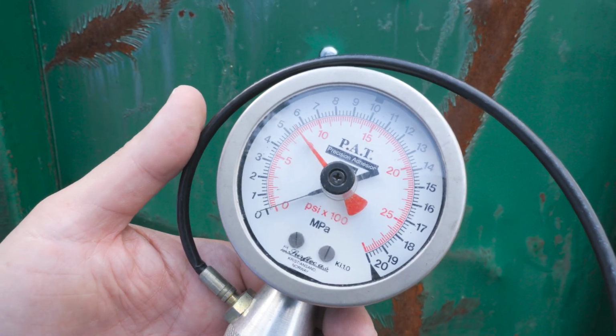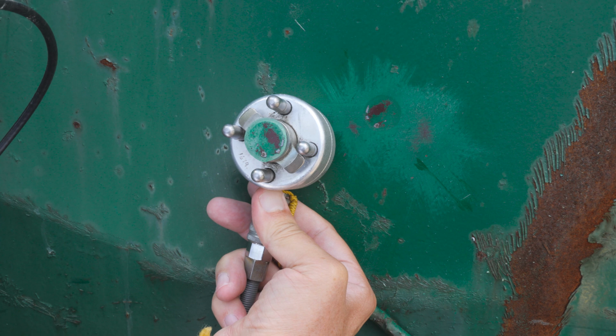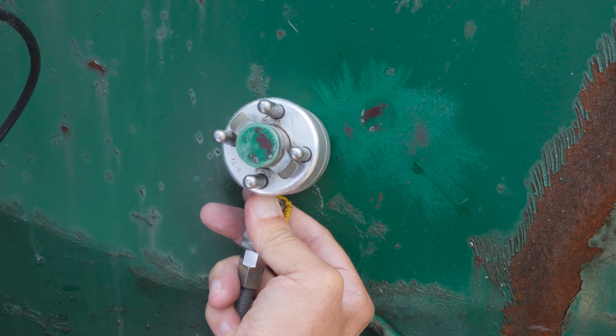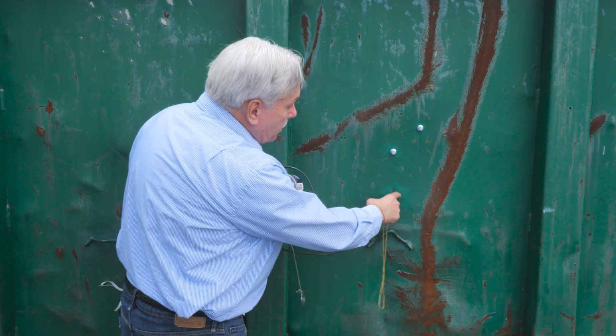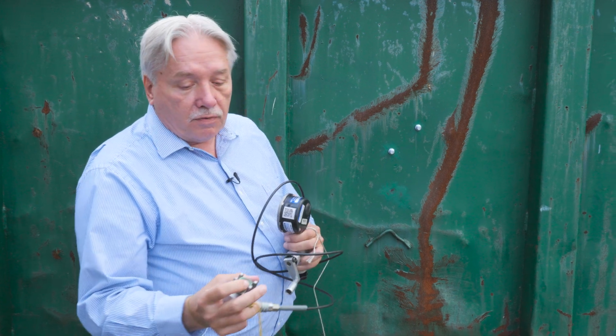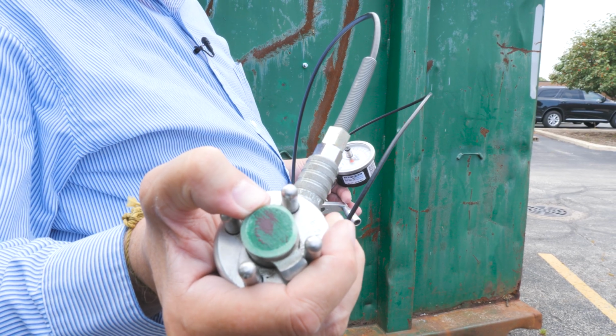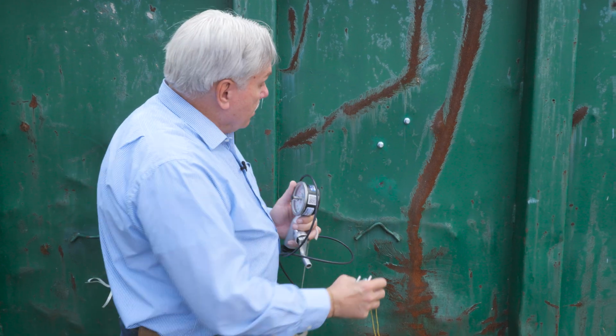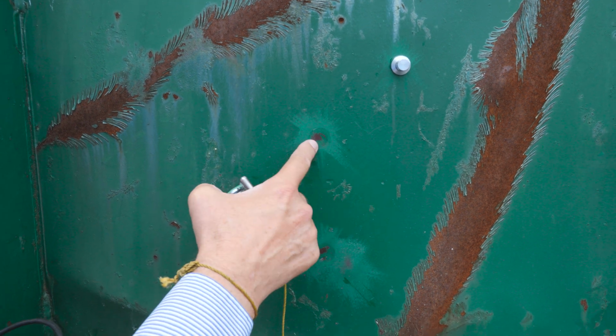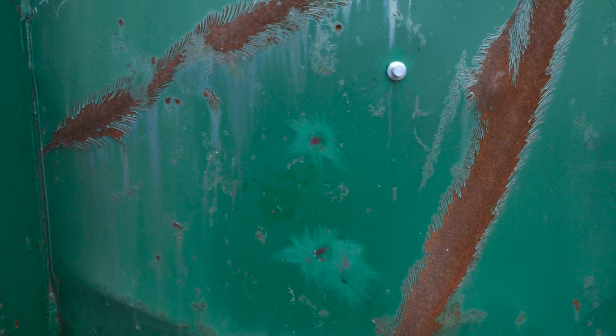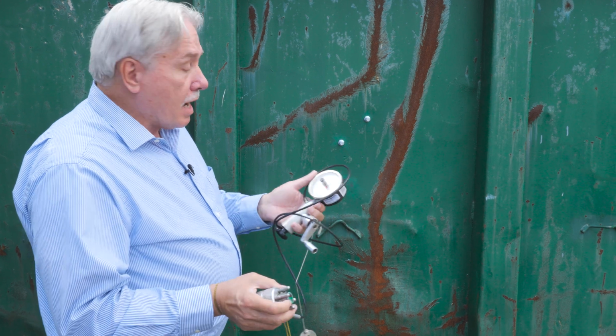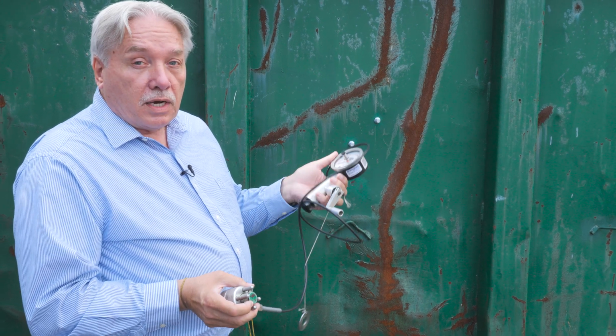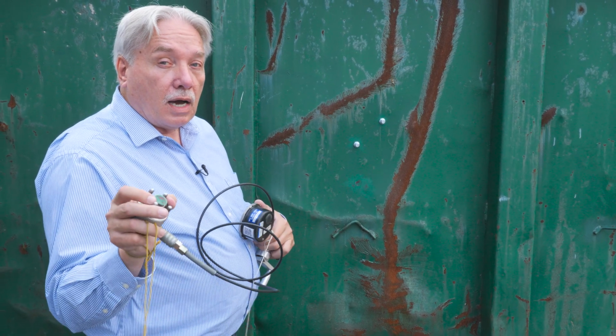We get two things out of this. One is we're able to see this one came off at 800 PSI. We also get some information on the dolly because it tells us where was the weakest plane of failure. And we can see that about 80% of it came off between our green coating. And then the other 20% came off between a brown primer. So we collect not only what the stress is, but we also collect how it failed.